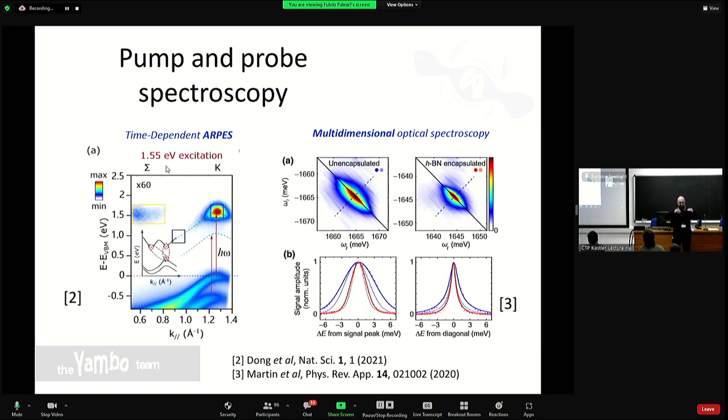And this causes the various energy levels to be a bit misaligned, for example, in absorption experiments, but also in luminescence experiments. And this adds a lot of noise to the broadening, to the width of the peak. But with this technique, you can actually remove all this noise and get to the true, or so-called homogeneous, line width of the system, which is the one that we compute when we do first principles calculations.